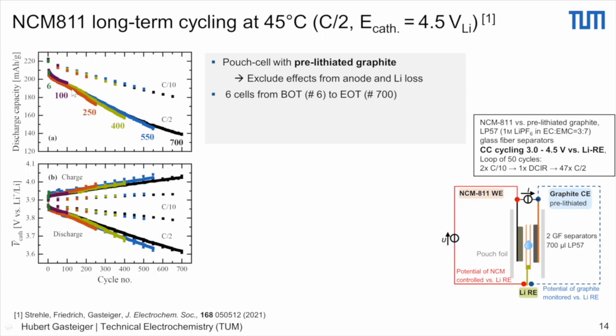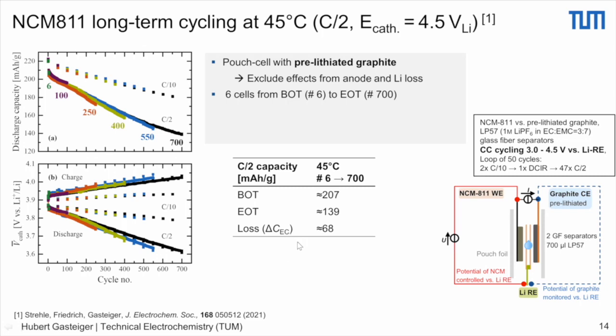And what you can see is that the capacity fading of these six cells follows each other very nicely here at C/2 and here at diagnostic cycles at C/10. The same is true for the voltage fading. So you get a decrease in the average discharge voltage and an increase in the average charge voltage due to the buildup of impedances. And if we look at the capacity loss for this experiment over 700 cycles at 45 degrees at this rather high cutoff potential, we lose about 68 milliamp hours per gram, which corresponds to about 33%